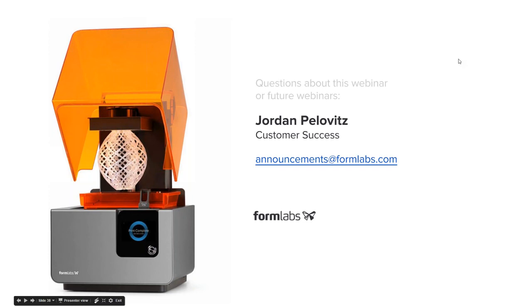Which is the best way to print some features that have some depths? For example, a box has holes with depth embedded on the model. Is that the same way with the cup example? Yes, I think I understand what you're saying. If the box is basically a solid box but with holes in it, those holes should be pointing towards the build platform, but slightly outwards so that air can get in and out. What you're trying to avoid is a completely enclosed cavity. So as long as you're avoiding that, it should be fine.